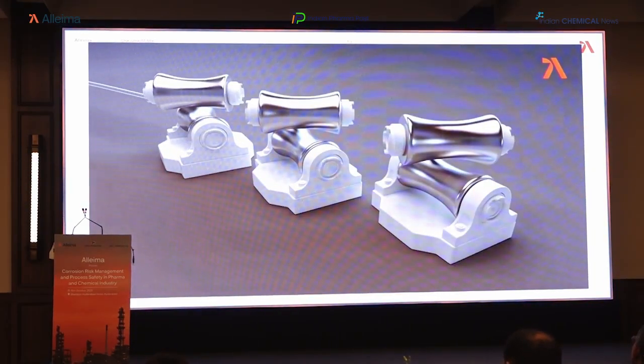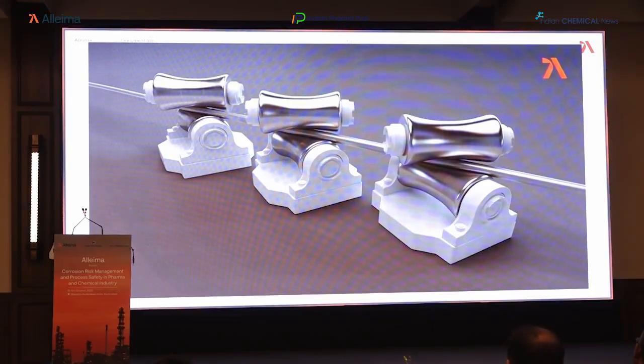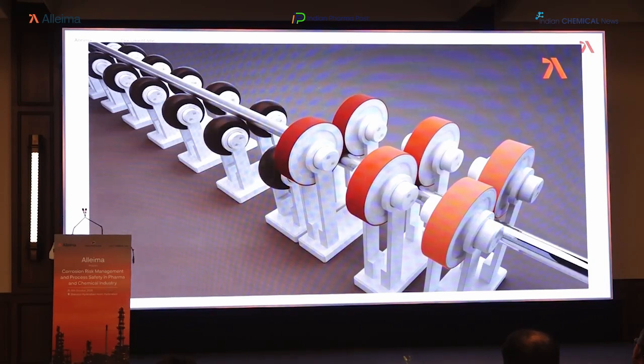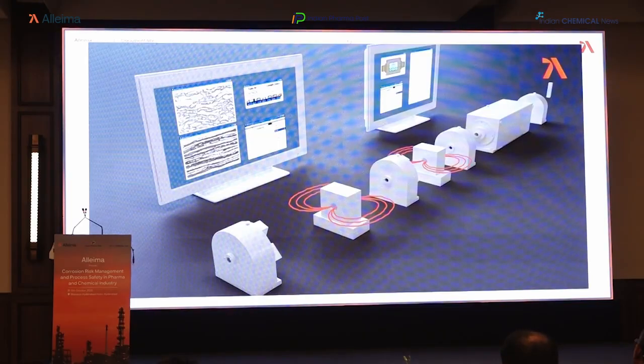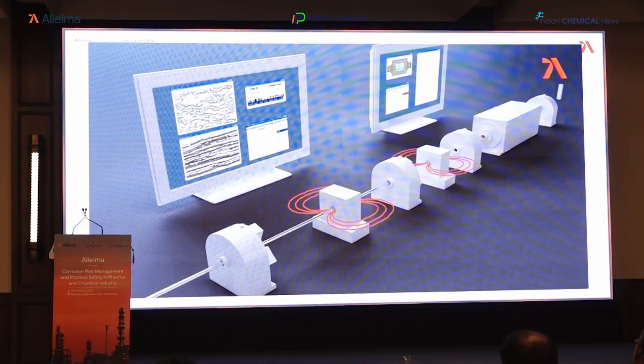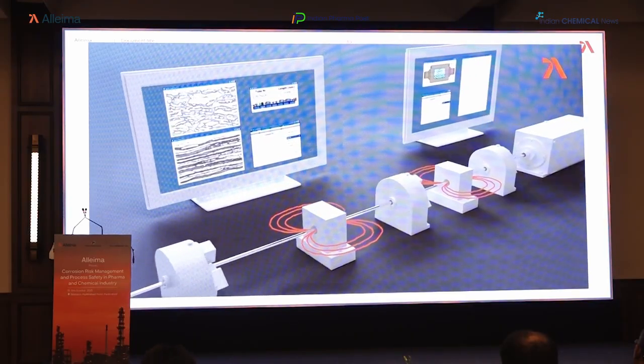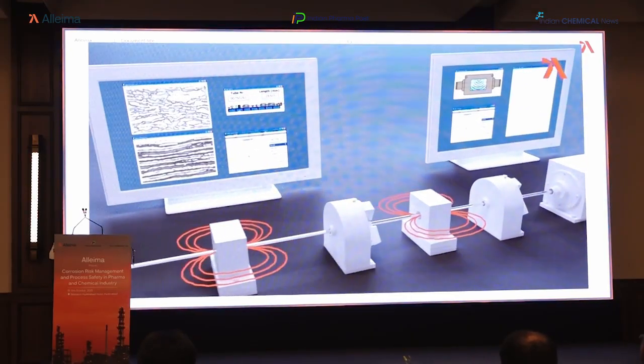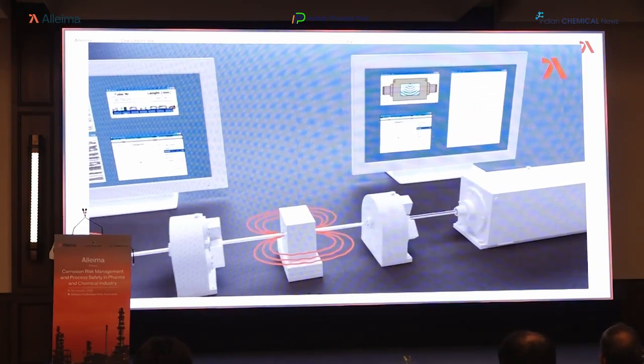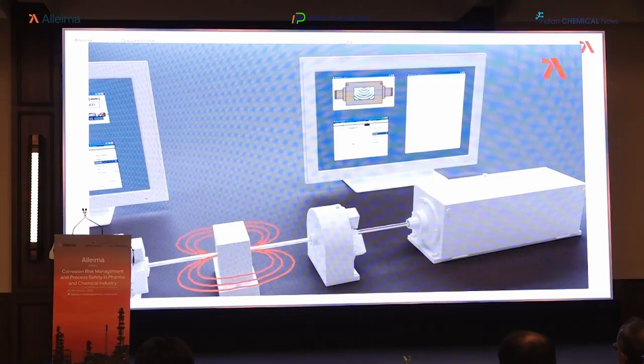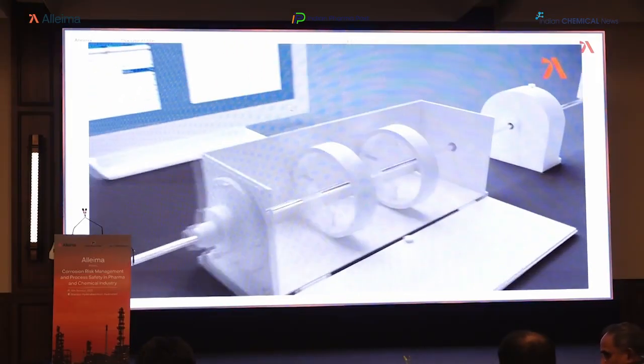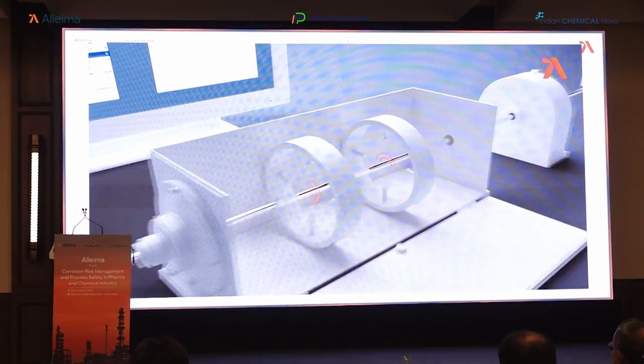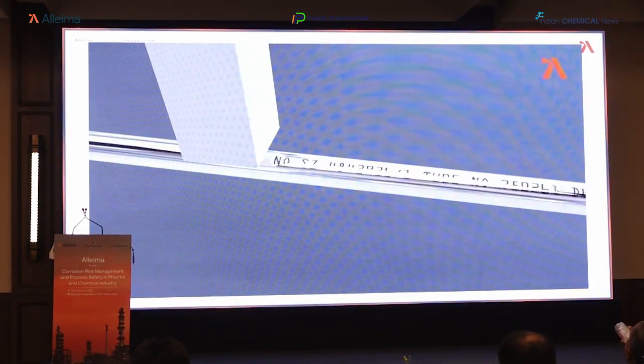The tubes are straightened, polished, and thoroughly cleaned. According to customers' requirements, the tubes are fully inspected for defects using ultrasonic and eddy current testing methods set to detect the tiniest defects such as cracks, cavities, or other material defects that the naked eye can't detect. Their dimensions are verified and they are also checked to ensure they are free of intermetallic phases. This is followed by visual inspection.